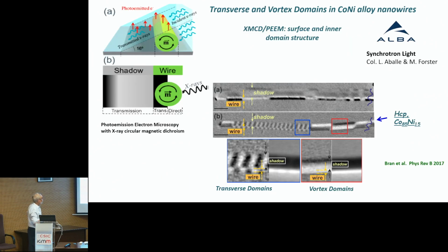But when we change the composition and we have a cobalt 85 nickel 15 with a large content of cobalt, we have a very different magnetic domain structure. For that, we have been making a number of studies in Barcelona in the ALBA synchrotron to investigate the domain structure and the domain process of individual nanowires. So in fact, we are profiting of this cylindrical shape of the nanowires.